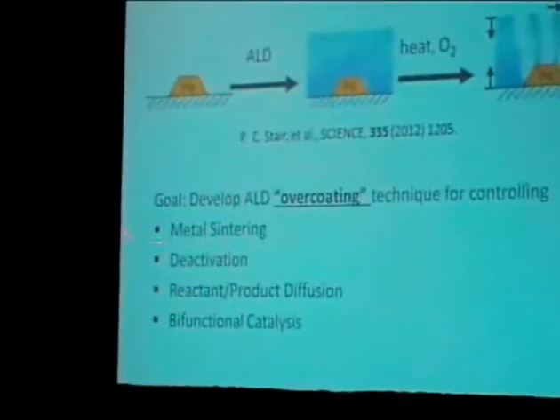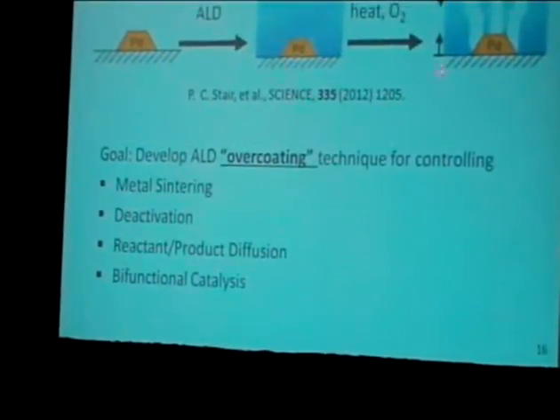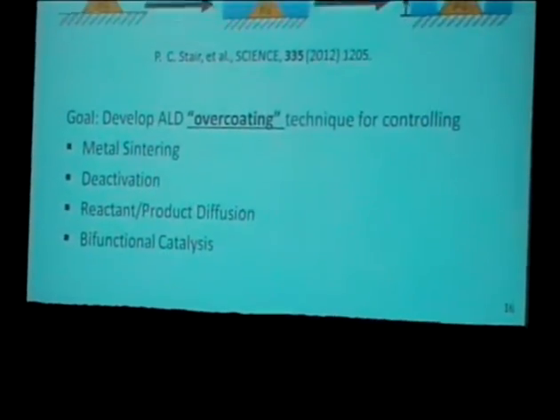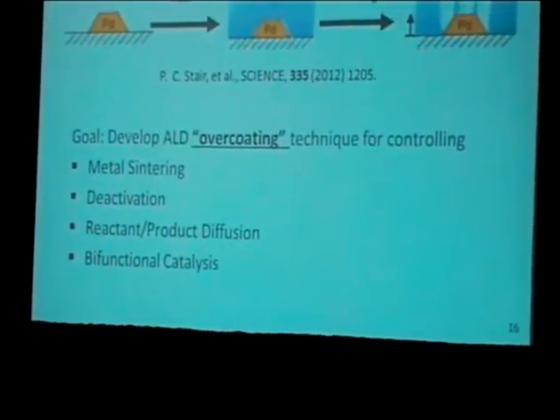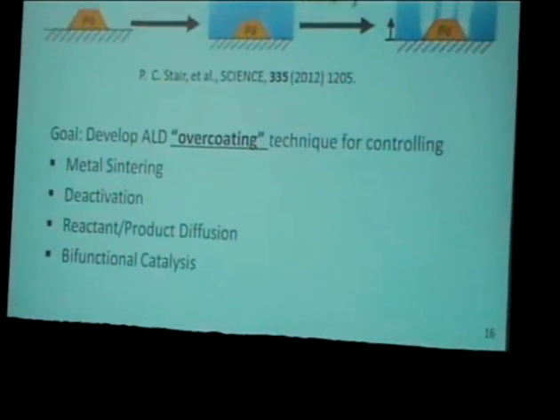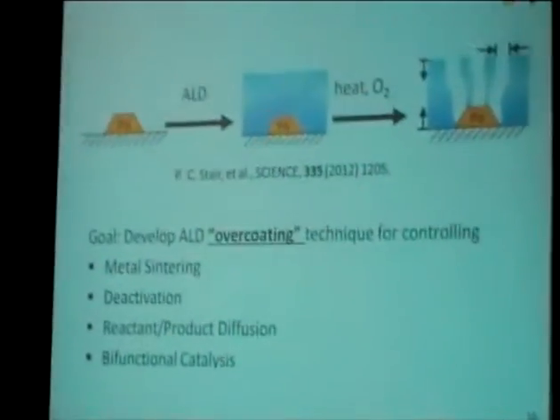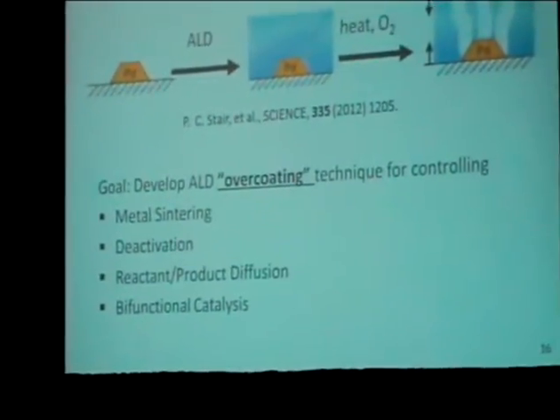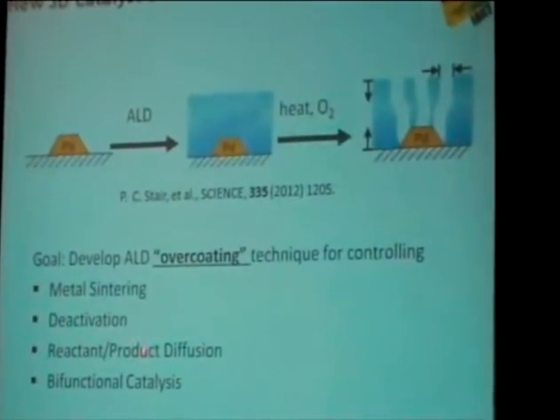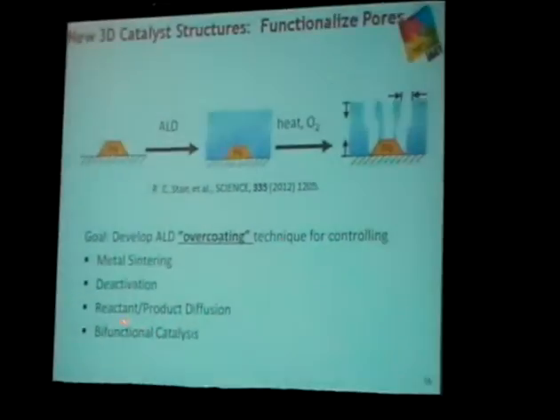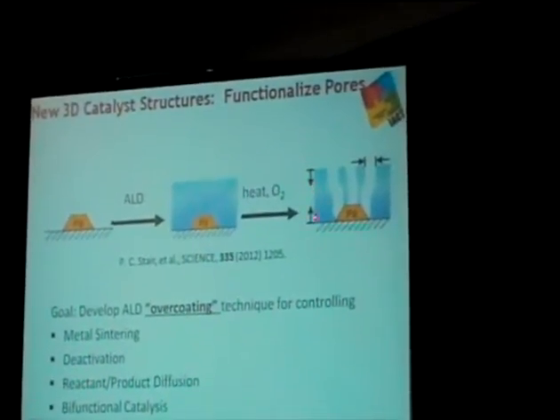So we've been using ALD overcoating recently to cut down on metal sintering. We actually build little domes over the catalyst, and there's no way for the two materials to get together. Sintering has been a common theme throughout this morning's talk. We're also interested in cutting down the deactivation and controlling reactant and product diffusion. And we're not only just putting alumina here, we're actually putting different layers on the sides of these catalysts for creating bifunctional catalysts, for example, hydrogenation activity coupled to an acidic component.